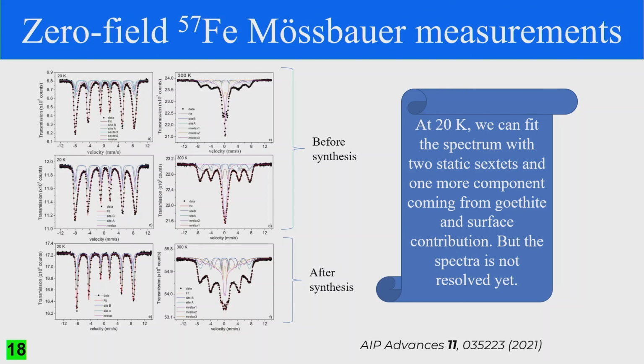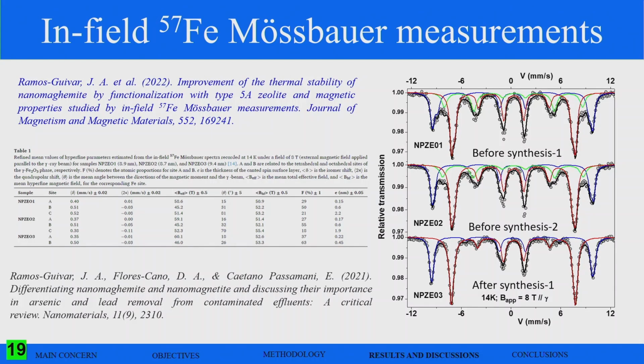So we need to apply a high field, in this case in-field 57Fe Mossbauer measurements. This is something we did with Jean-Marc's lab to finally resolve this problem of nanomagnetite versus nanomaghemite, which has been in the community for years, as I have seen in these last 10 years of studies. We published that in a review last year that differentiates the importance of magnetite or maghemite for environmental applications. And this year also, we found that a secondary phase can form, confirmed using in-field Mossbauer spectroscopy. This phase is goethite, but it's not seen by X-ray diffraction, as I show you in the sample of ammonium co-precipitation.